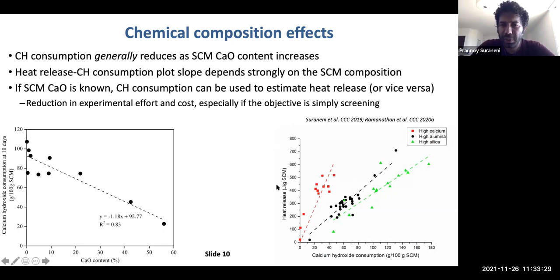Second, we showed that the heat release versus calcium hydroxide consumption graph, the same graph that you saw before, depends very strongly on the chemical composition of the SCM. Specifically, the lowest slope is seen in materials which are high in silica. Aluminosilicates, which are relatively high in alumina, show a medium value of the slope. And the high calcium materials like slag show the highest value of the slope.